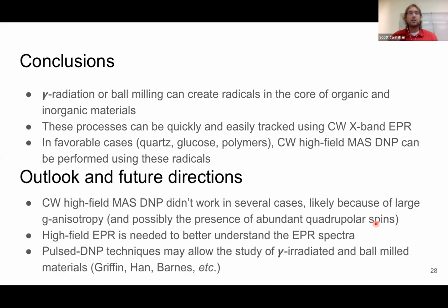So what still needs to be done? Well, on some of these samples it didn't work. It's probably because they had a high g anisotropy, or there was a large presence of abundant quadrupolar spins, which create hyperpolarization sinks, which take the polarization away from the nucleus we want to look at.